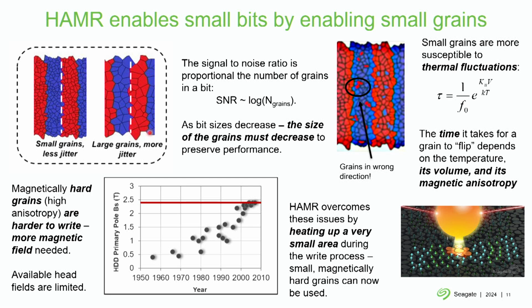But the goal here is, yes, we need to decrease the bit size. However, small grains are susceptible to thermal fluctuations. This material is a magnetic material, and magnetic particles try to switch their magnetization with a frequency that depends on the temperature, it depends on their volume, and depends on their magnetic anisotropy. So if I don't change anything else in the media and just decrease the grain size or particle size, these grains will attempt to flip more often, and that's not good because I need my data to be stable over many years.